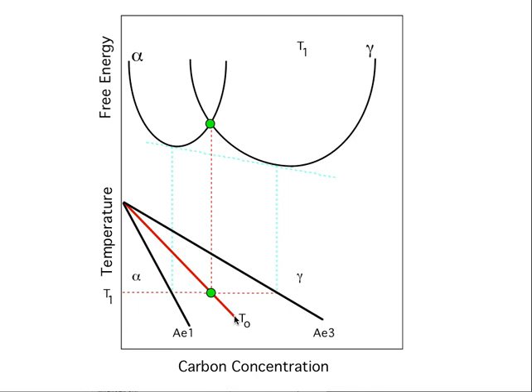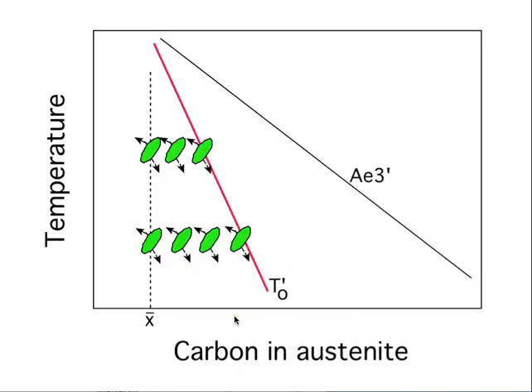Basically, it tells you that if the carbon concentration of the austenite exceeds the T0 curve it is impossible to get diffusionless transformation, and we decided that bainite forms without any diffusion. If you conduct isothermal transformation and imagine that a plate of bainite forms like martensite, you will partition carbon into the austenite; the austenite becomes richer in carbon and this process can only continue until you hit the T0 curve. If carbon was never supersaturated in ferrite then it would continue until the equilibrium phase boundary, which is the A3 phase boundary. The dashes simply imply that we are taking account of strain energy due to transformation.